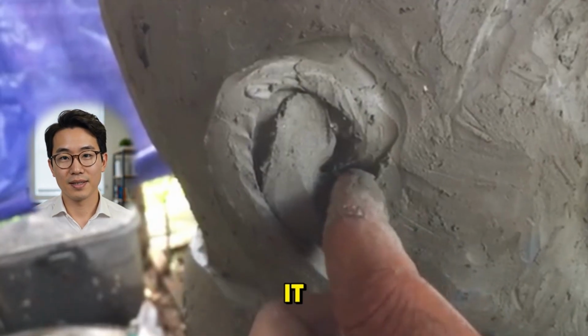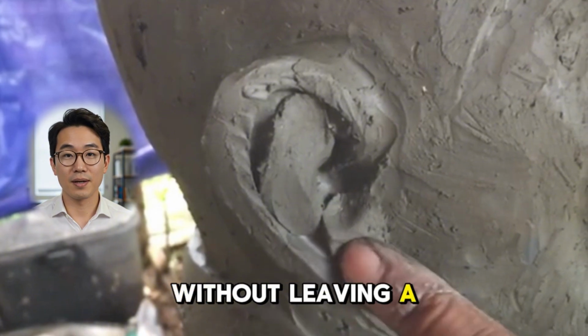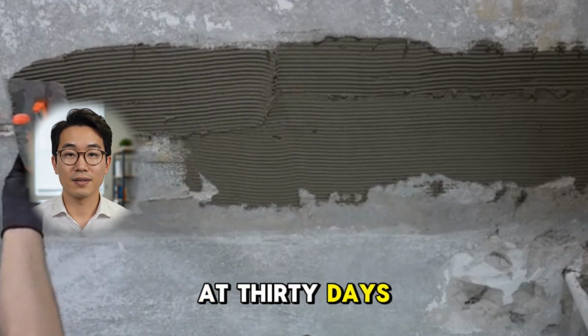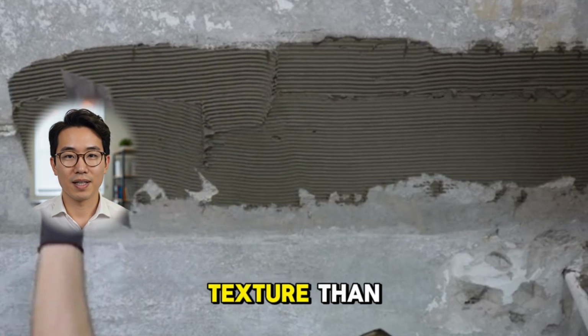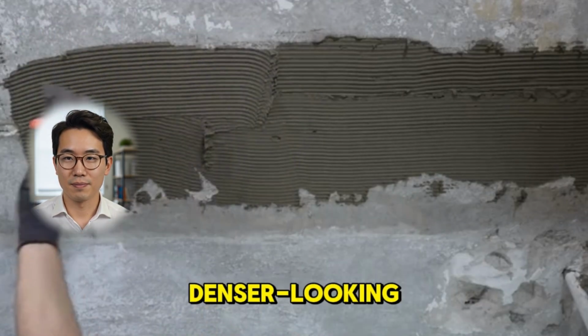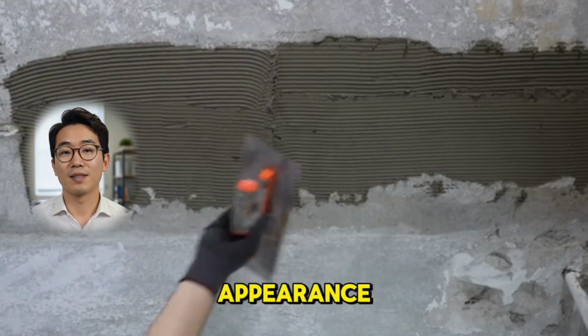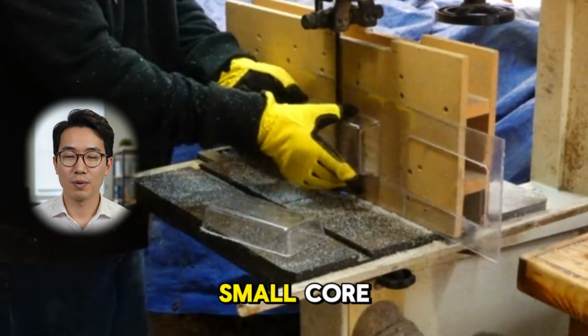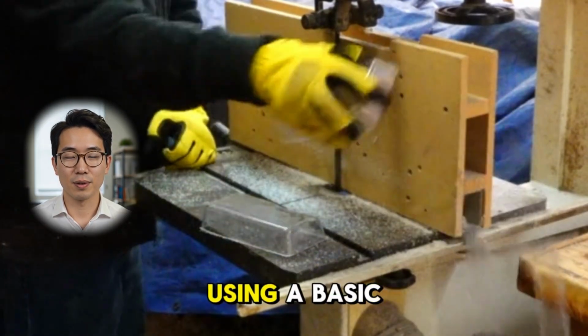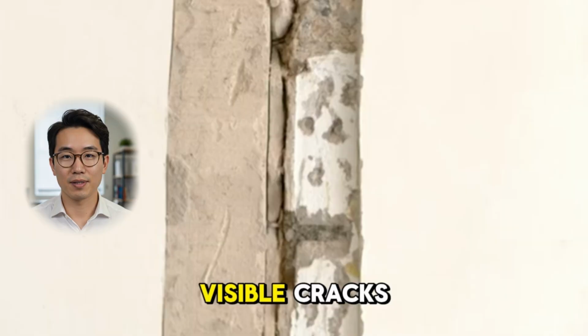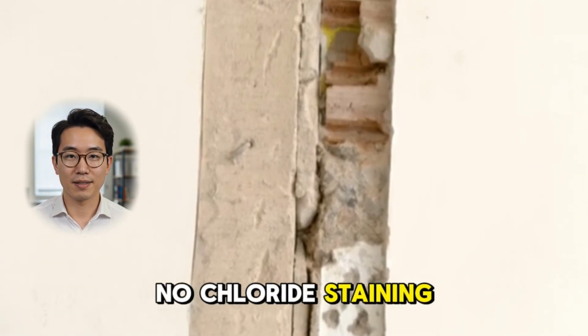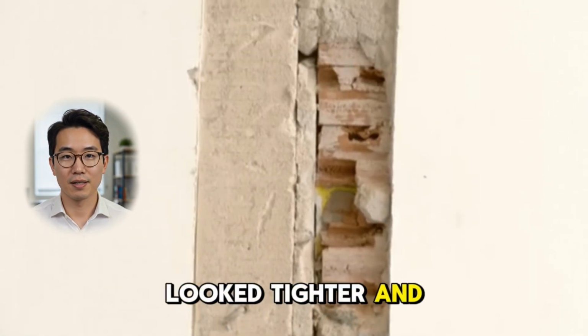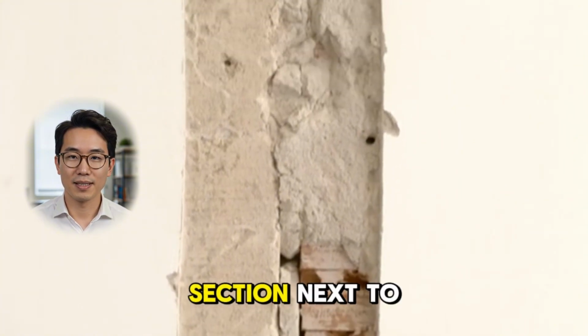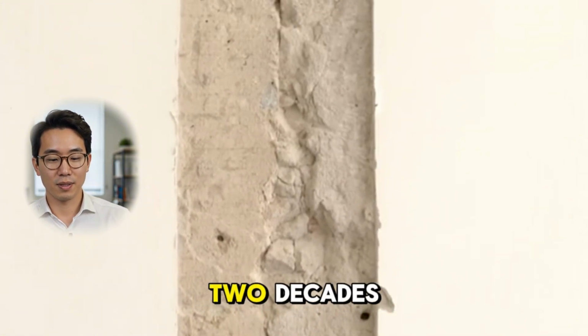Within 3 days, it had set hard enough to touch without leaving a mark. At 30 days, the surface had developed a slightly rougher texture than Portland cement mortar, denser looking, more mineral in appearance. At 12 months, David pulled a small core sample from the repaired section using a basic masonry drill. There were no visible cracks, no chloride staining. The interior of the sample looked tighter and more uniform than the original Portland cement section next to it, which had been there for over 2 decades.